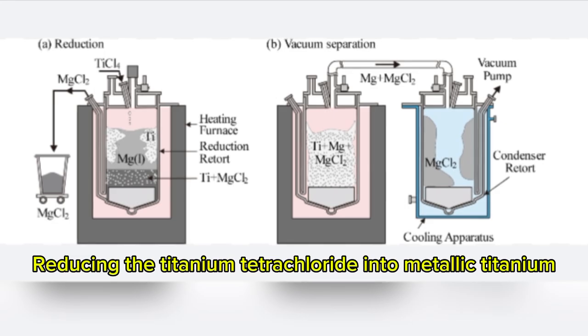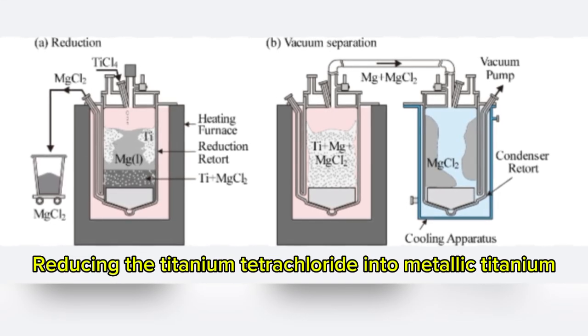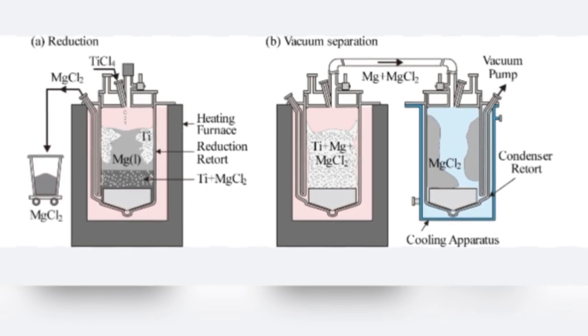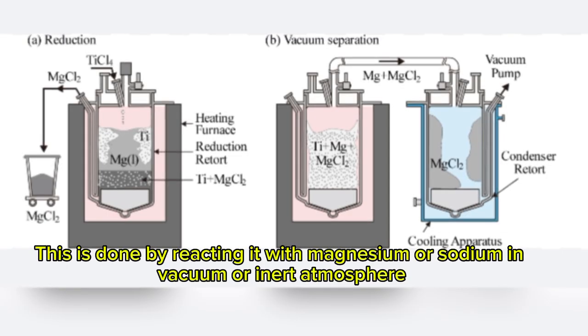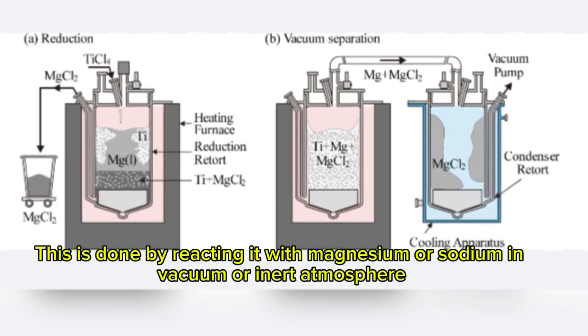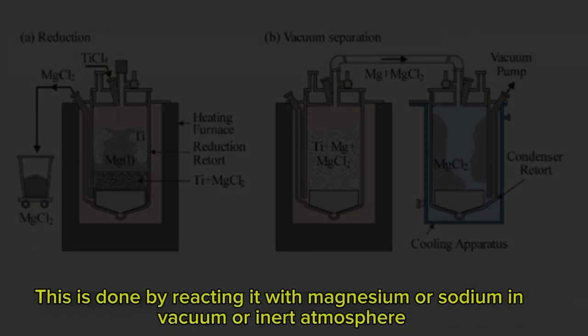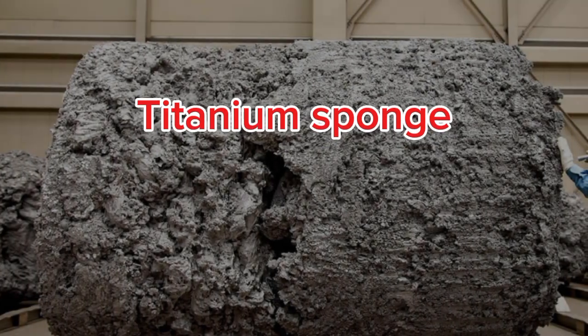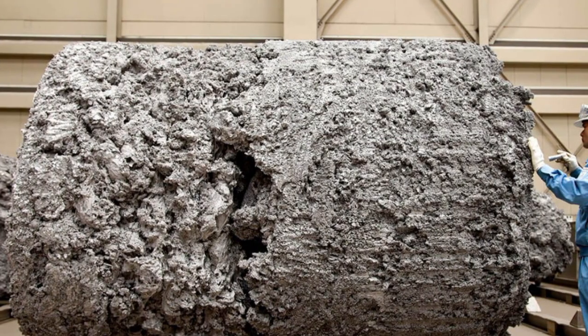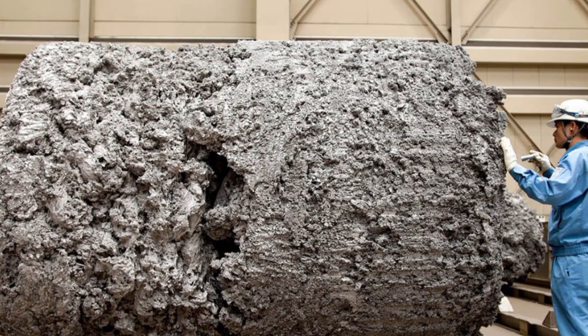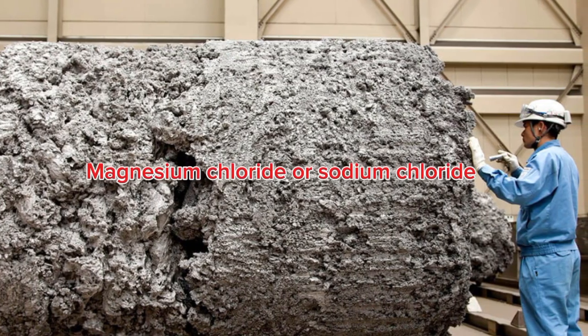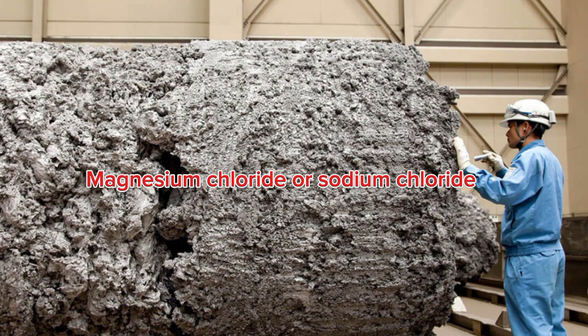The next step is reducing the titanium tetrachloride into metallic titanium. The purified titanium tetrachloride reacts with magnesium or sodium in a vacuum or inert atmosphere. This reaction produces titanium sponge, a porous, rough form of titanium, along with byproducts such as magnesium chloride or sodium chloride.